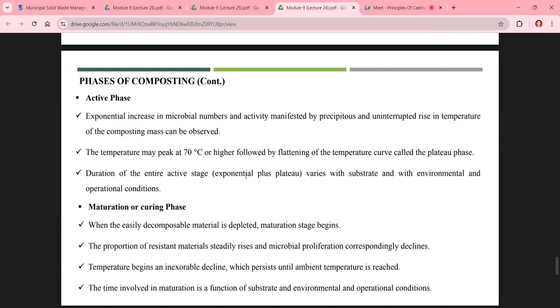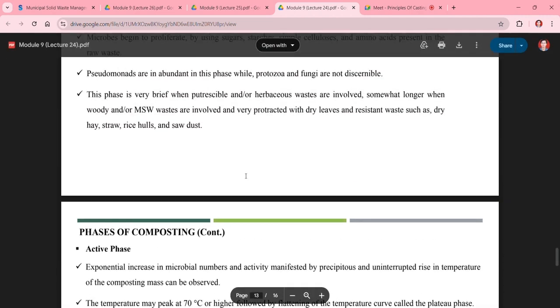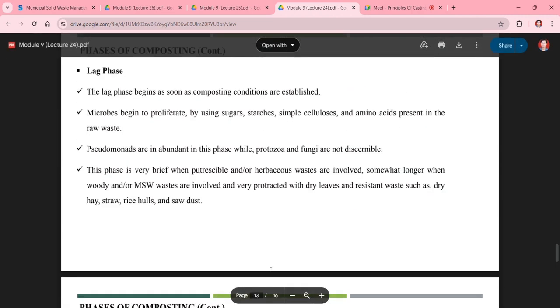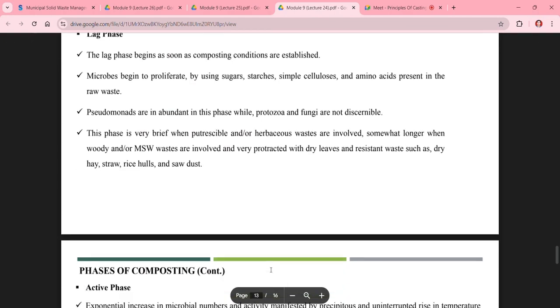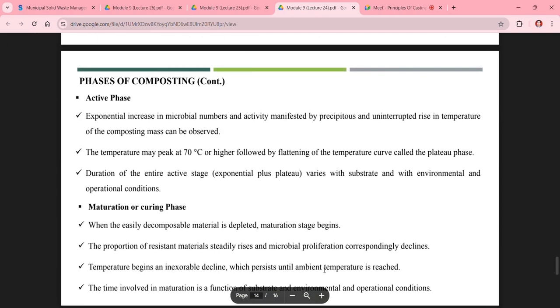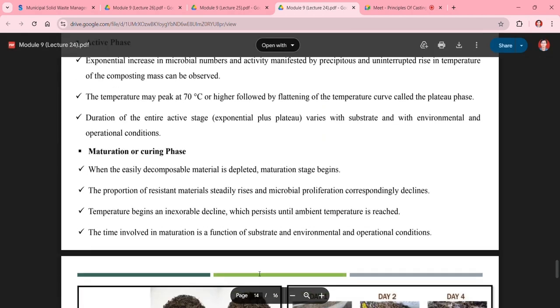Then coming to the active phase, in this phase an exponential increase in microbial numbers will happen, and activity will be manifested by a precipitous and uninterrupted rise in temperature of the composting mass. The peak temperature can be observed at around 70 degrees Celsius during this phase, and the duration of the entire active range varies with substrate and with environmental and operational conditions. So the duration of the lag phase varies according to the composition of the waste material, and the duration of the active phase is dependent on the environmental and operational conditions.